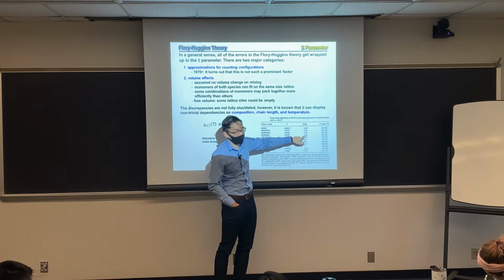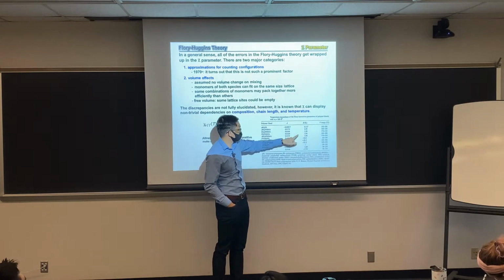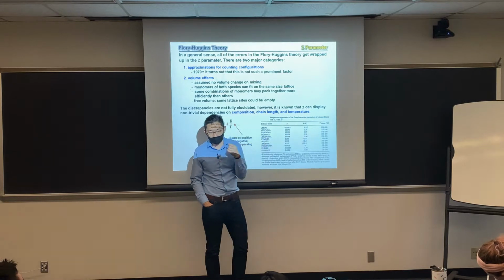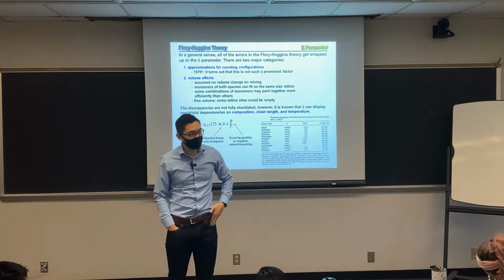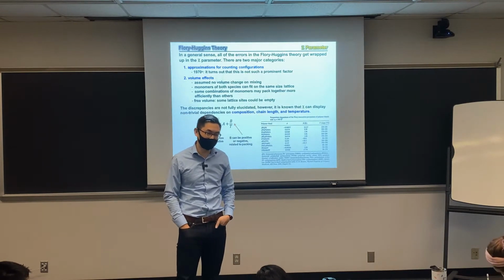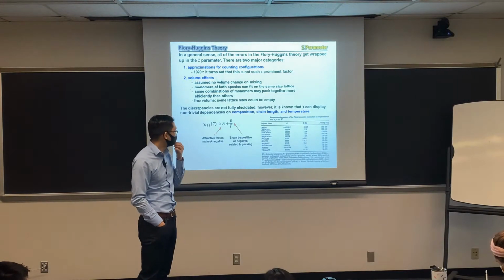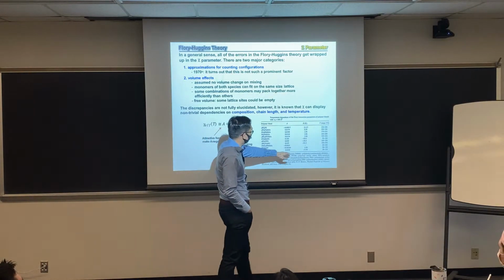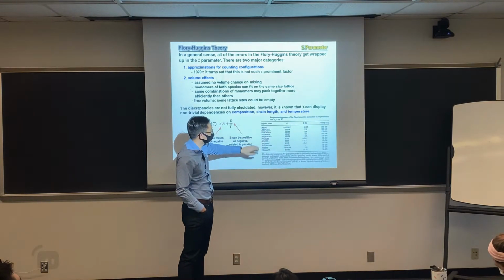So when the temperature goes up, the chi parameter between PS and PMMA will drop. If the chi drops, it means they are more likely to mix, so a way to promote mixing can be heating the PS and PMMA up to a relatively higher temperature. It also tells you the temperature range that was measured. So this gives you some useful information.